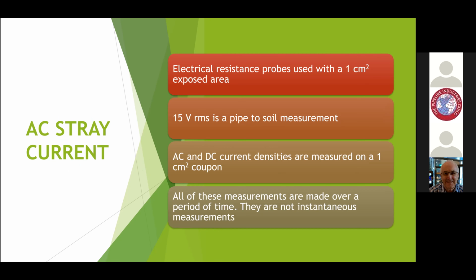There is a device called an electrical resistance probe, which has a 1 centimeter square exposed surface area. And this probe works in a very special way, because we know how to measure and how to calculate the resistance of a 1 centimeter square piece of steel. And we know that there's a relationship between the resistance and the surface area. Actually, the smaller the steel, the higher the resistance.